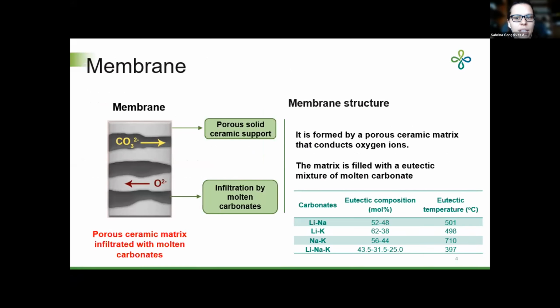So this image is a simplified sketch of the membrane. It's formed by a porous conductive oxygen ion ceramic matrix that is filled with a eutectic mixture of molten carbonate. This matrix can be produced using different methods, such as cold pressing, tape casting, deposition, and many others. But the important thing is that after sintering, it remains porous, so it can be infiltrated by the molten carbonate. And usually, eutectic mixtures of carbonates are used to lower the melting temperature. And it's possible to choose the best mixture depending on the temperature of use and the conductivity of each one.